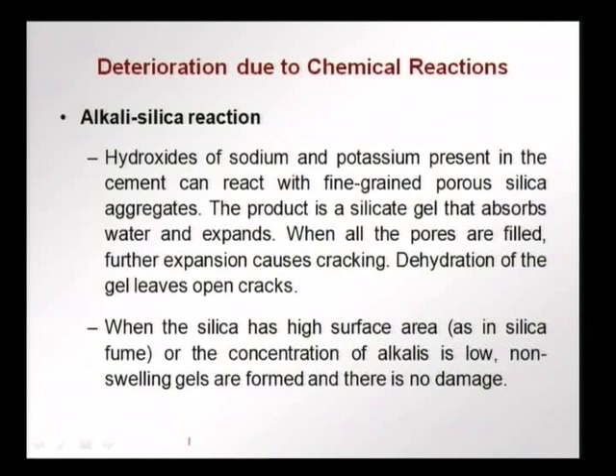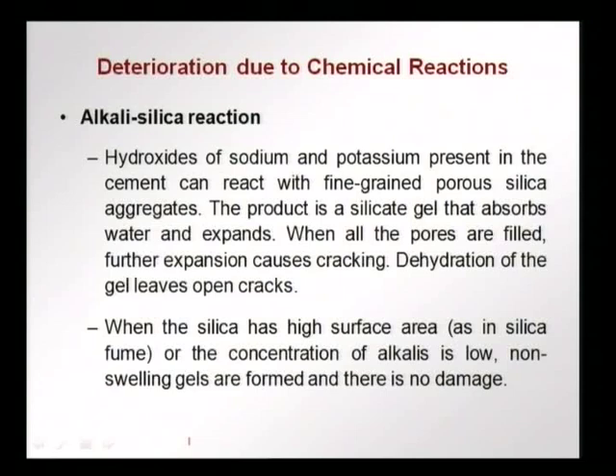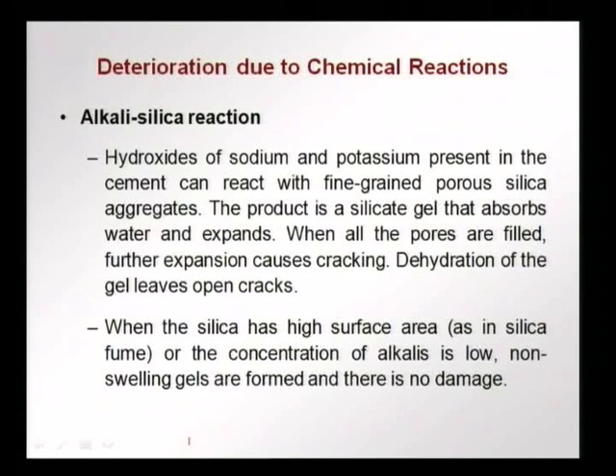ASR only occurs when reactive silica is present in the aggregates. When very fine silica such as silica fume is used — with very high surface area — or when the alkali concentration is very low, the gel formed is non-swelling and no damage occurs to the concrete.